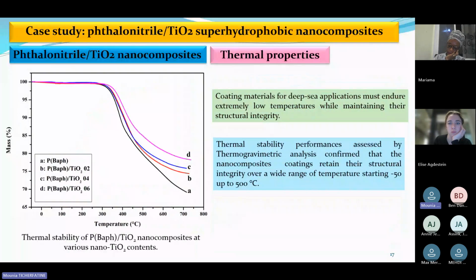Also, thermal properties were investigated, as coating materials for deep sea applications must endure extremely low temperatures while maintaining their structural integrity. Thermostability performance assessed by thermogravimetric analysis confirmed that the nanocomposite coatings retain their structural integrity over a wide range of temperature from -50 to 500 degrees Celsius.